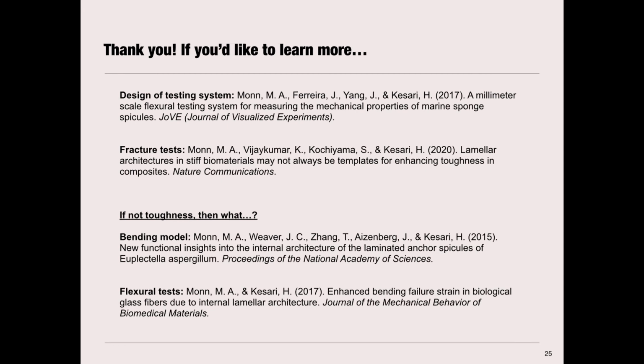Yeah, in brief, you can think of it like this: as the crack is growing towards the interface, if it's growing towards a flat interface, it sees a plane of weakness and can nucleate daughter cracks ahead of the primary crack anywhere in that plane. Whereas if you have a curved interface, the crack's only really seeing a line of weakness. It's seeing that first cusp of the interface, and as you move further along the interface, away from that line, you're also moving further from the crack tip, so the stress is lower there. So it's very constrained in how it can grow.